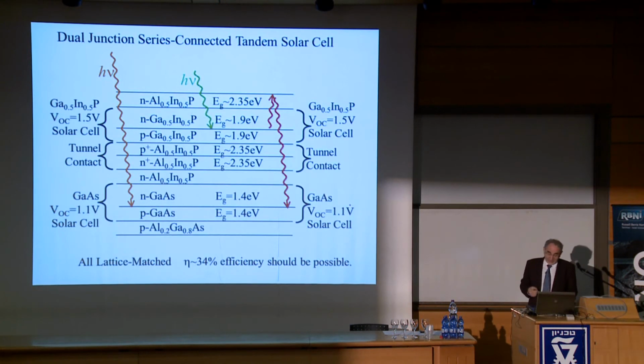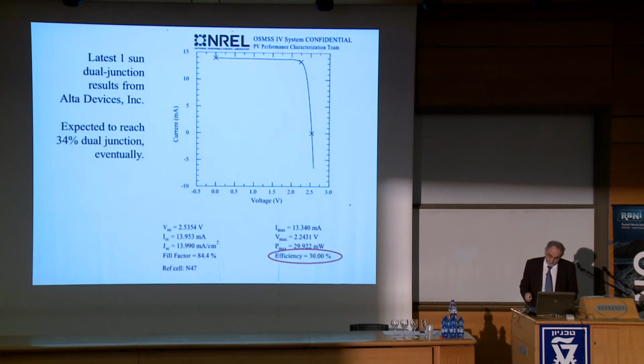We're almost done. And actually, I was supposed to show you some of these solar cells from Alta. I'll show them to you in just a minute. They're just made of gallium arsenide. They're very thin, about a micron thick. And they lend themselves to dual junction because you can grow this alloy on top. And then you have a very interesting dual junction cell, lattice matched, relatively easy to manufacture, and with interesting radiative coupling, the luminescence couples between the big band gap and the small band gap and so forth. So the net result is that you have more performance.